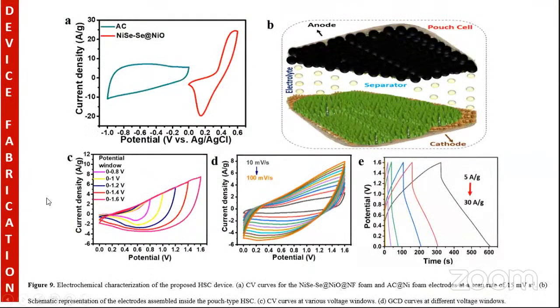Finally, coming to the device fabrication part, out of all the three electrodes, I've already shown that the nickel selenide nanotubes grown over nickel oxide nanoflower morphology showed the best performance. So we have taken that as a cathode. Activated carbon on nickel foam, we have taken as the anode, and we have separated them with a filter paper in a 1 molar KOH electrolyte solution, and we have made a pouch cell out of it. Then this is the CV performance of individual activated carbon, and this corresponds to the NiSe at NiO electrode.